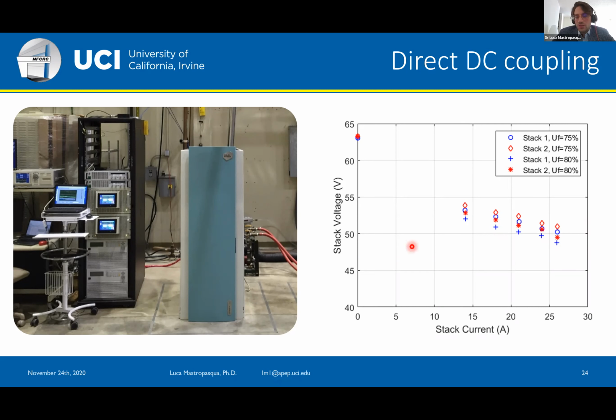As always, we characterize the stacks first of all. Here I've reported an example of the polarization curve for the two stacks, stack 1 and stack 2 in blue and red, for this commercial system.